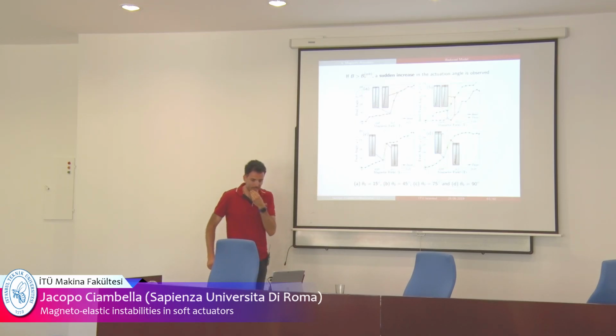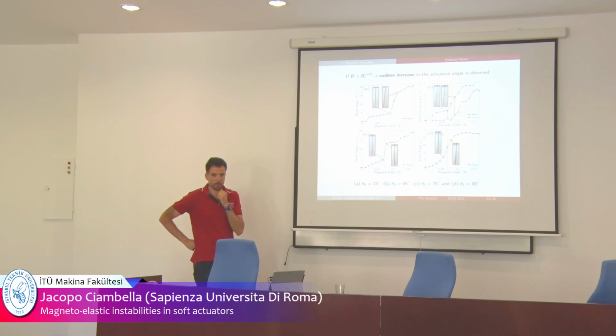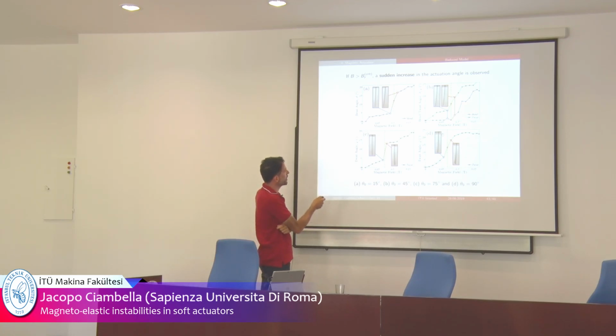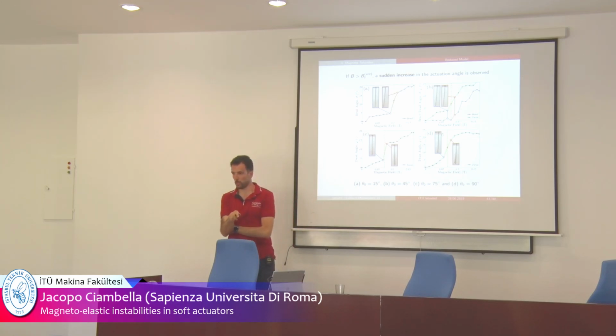And these are again experimental results. So in terms of magnetic field, this is the 0-degree specimen. And this is the bending angle here, and this is the twisting angle. No, sorry, this is only the bending angle, because for 0 degree we didn't observe any twisting. So you only have bending. Okay, this shows how the bending angle changes with the field. And so what we see is that it bends a little bit, up to a certain value of the field where you have an immediate bending. So the bending angle increased abruptly.